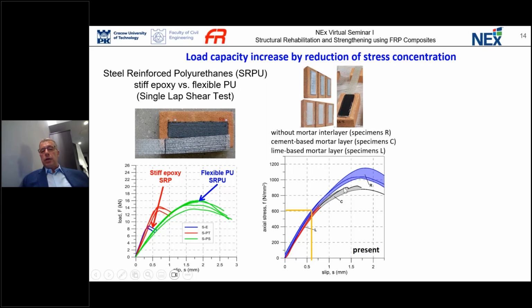So we did some such kind of comparison tests. Mainly, we bonded the steel fibers directly to the bricks. So this is this blue line. When we bonded the same system, but by interface, I mean cementitious layer, we received this kind of behavior. If we used very weak lime mortar, because this kind of material is used in heritage structures in Europe, in this case, we receive directly this red line.